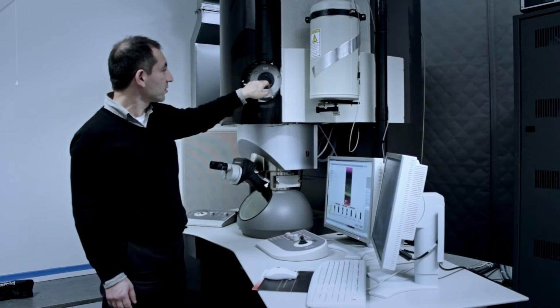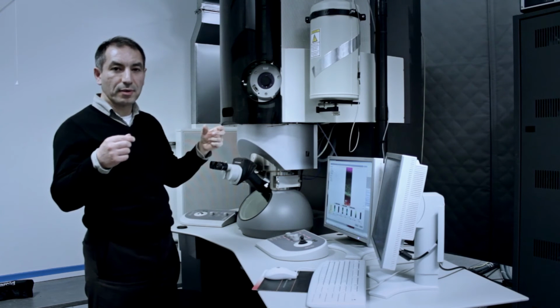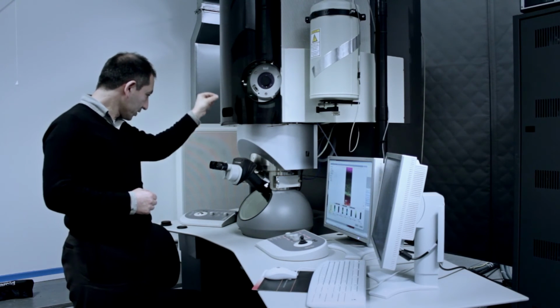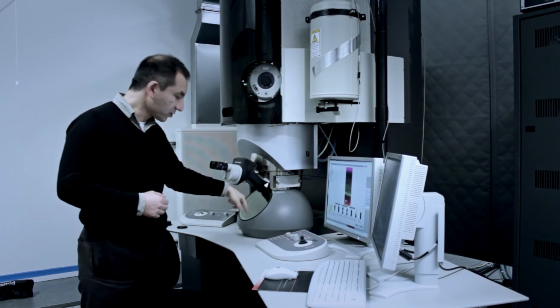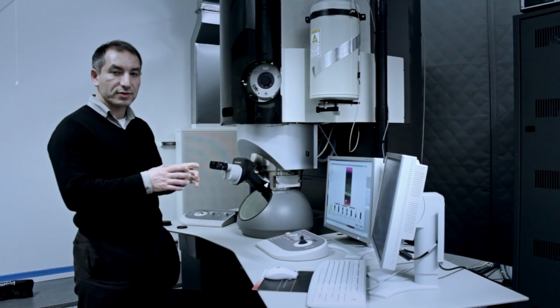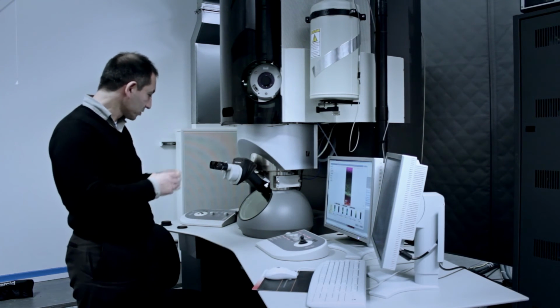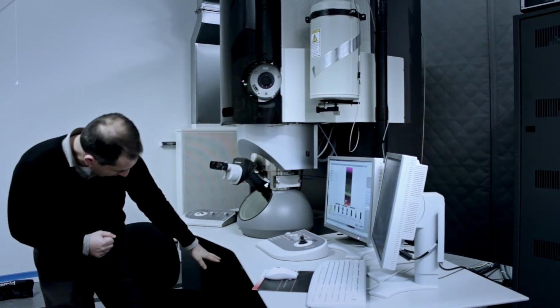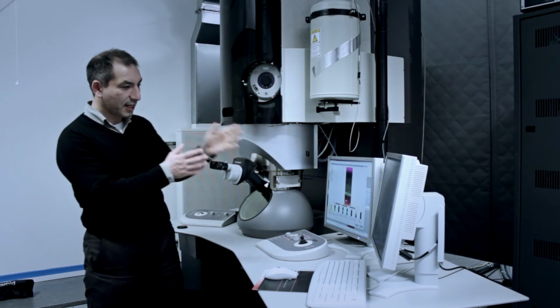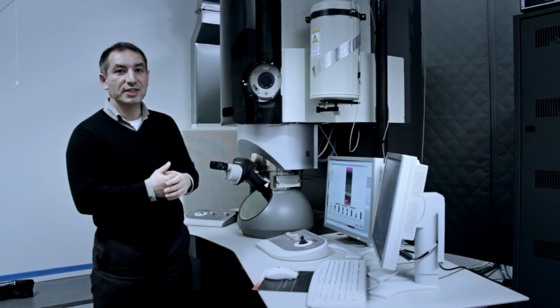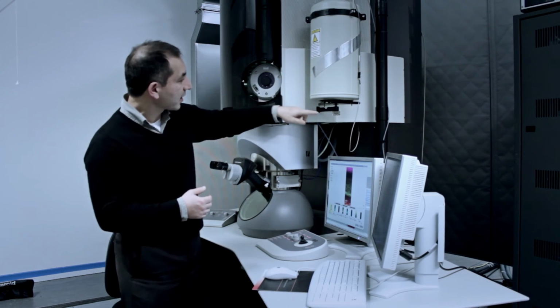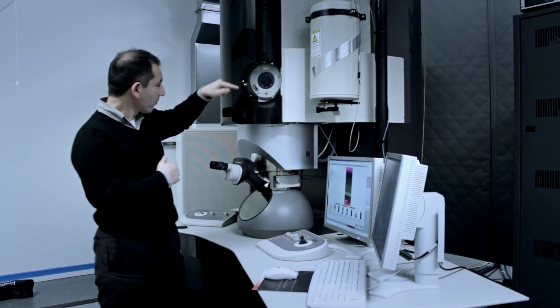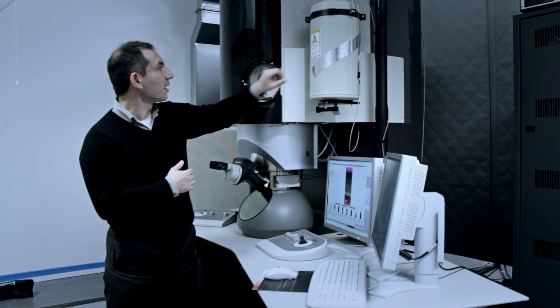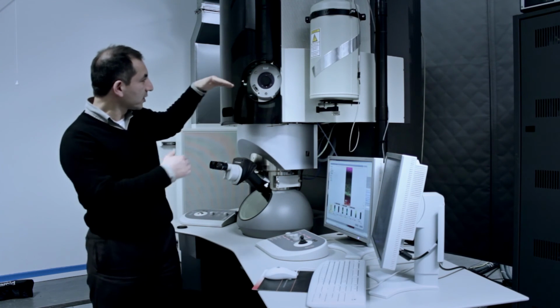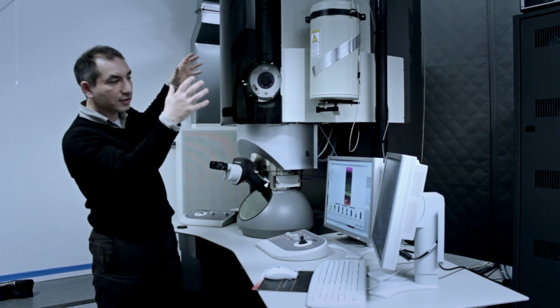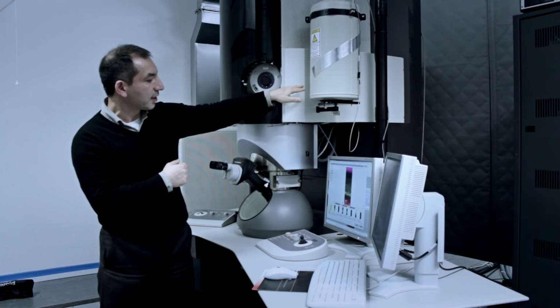The sample's inserted here in the sample chamber through the sample rod, and then the electrons go through the sample, hit the viewing screen here, which we view through a fluorescent phosphor screen. And then we also have cameras down here, so we can lift the screen and capture the image onto a CCD camera. We also have an EDS detector here, which is cooled by liquid nitrogen when the detectors are in position, and the X-rays that are generated around the sample are detected by the detector here and analyzed through the software.